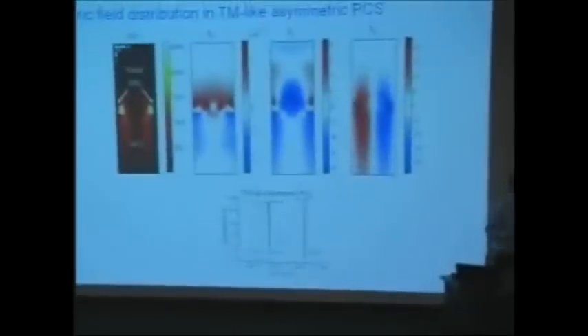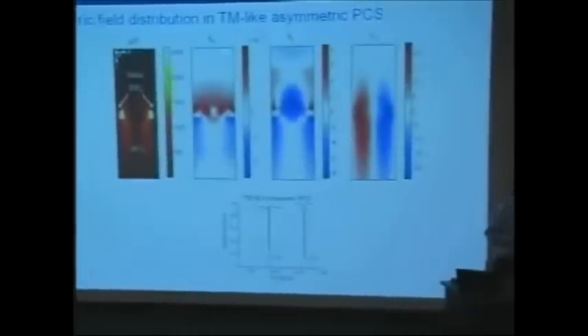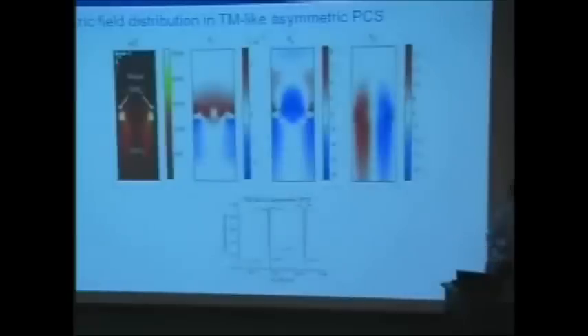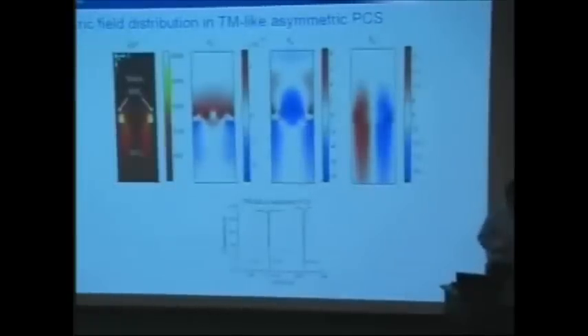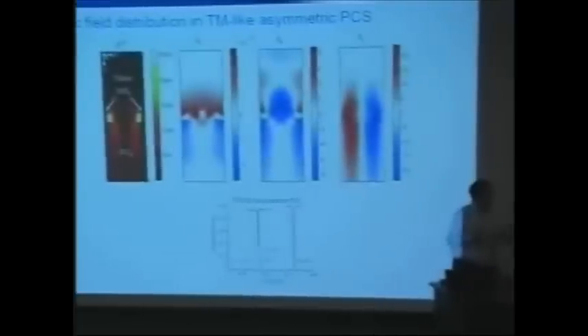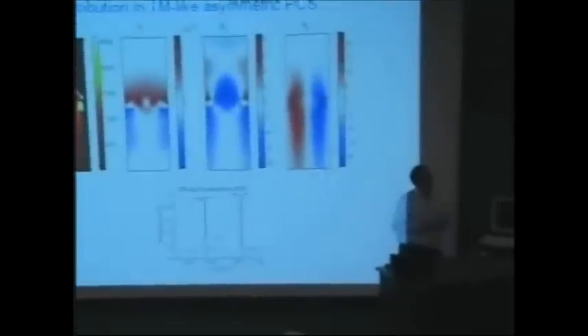in the middle. There are some groups, for example, the Cunningham group in Urbana-Champaign, that created a sponge layer by CVD that is sitting on the surface, and this is where the biomolecule sits. So depending on where you want it, you can create the sponge selectively either on the top surface or in the middle of your voids. It's part of the oblique CVD technique that allows you to make it. So it's something you could control.